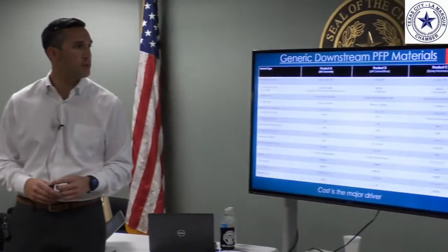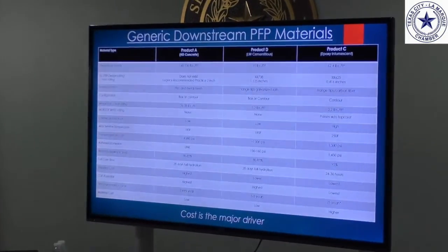Next, I want to talk about the weight for the 2-hour rating. Product A is 26 to 28 pounds per square foot. It's pretty heavy. Product D is 5.2 pounds per square foot. Not too bad. Product C, the epoxy intumescent, is 2.2 pounds per square foot.